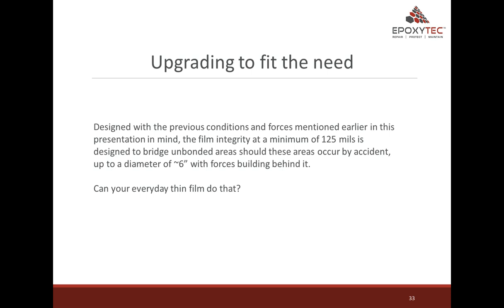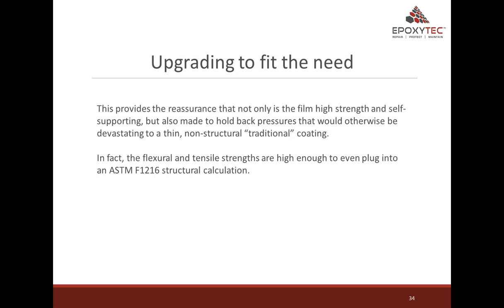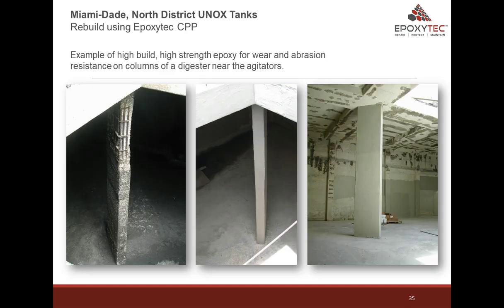Can your everyday thin film do this? This provides the reassurance that not only is the film high strength and self-supporting, but also made to hold back the pressures that would otherwise be devastating to a thin, non-structural, traditional coating. In fact, the flexural and tensile strengths are high enough to even plug into the ASTM F1216 structural calculation.